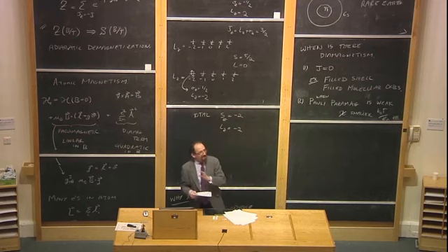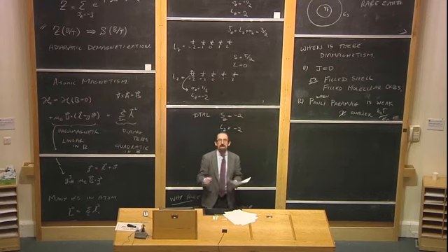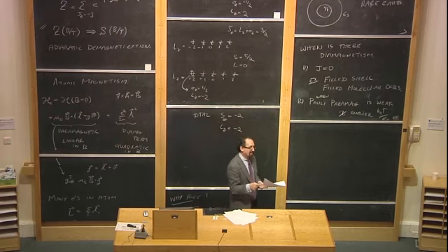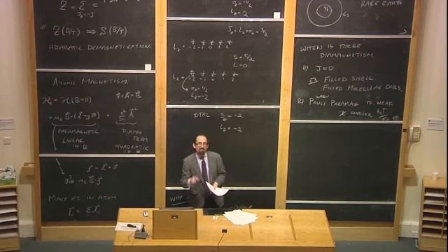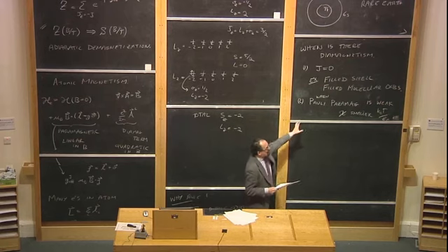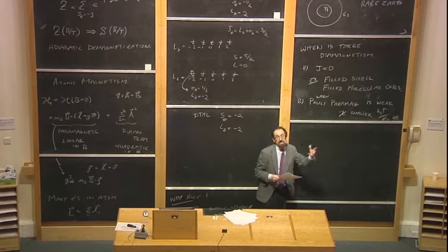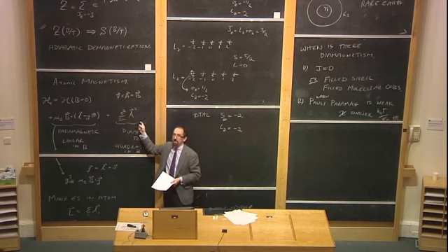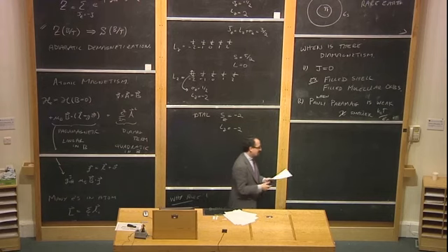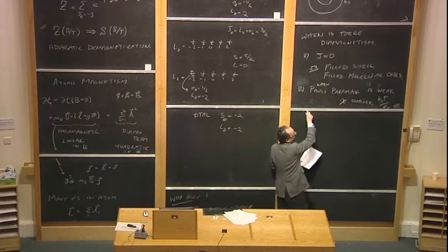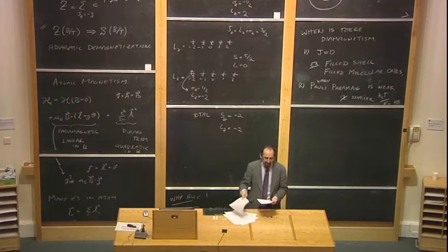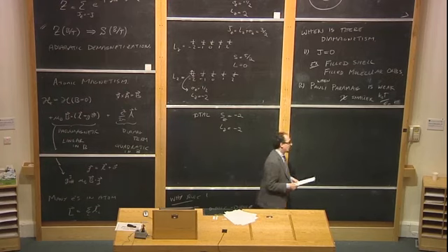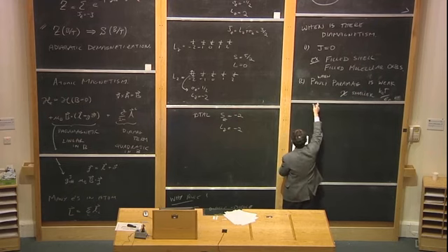And so here's a challenge. You should ask your tutors, is copper a diamagnet or a paramagnet? Unless they were tutoring this course last year, in which case students asked them the same question last year. So for new tutors, most of them will get it wrong. Most people will say that, well, it's a metal, so it's a Pauli paramagnet. And indeed, it has the Pauli paramagnetism physics, but that's so weak that the diamagnetic term here actually has a chance to compete with it. And in fact, for copper, it turns out to be diamagnetic, surprisingly enough. So with metals which have only Pauli paramagnetism, you can get diamagnetism winning overall. So challenge your tutors with that. See how many get it right.